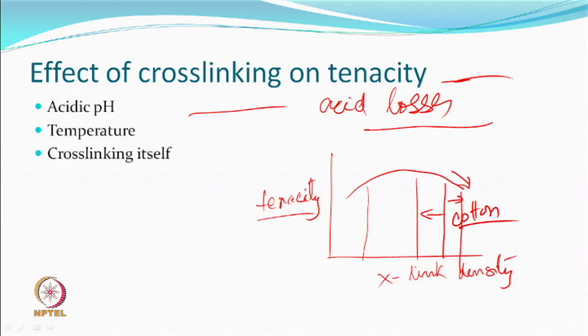On the other hand, if you have viscose which actually has a low crystallinity, and so on and so forth, overall cross-link density is less. In this case, reverse happens, that if you increase the cross-linking, the strength can increase. If you wet, the wet strength of viscose is low, right. So, you can obviously have this.